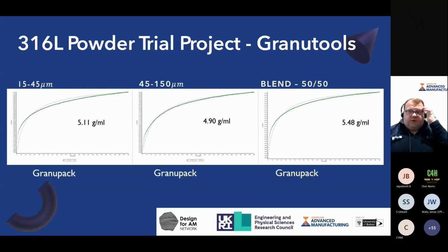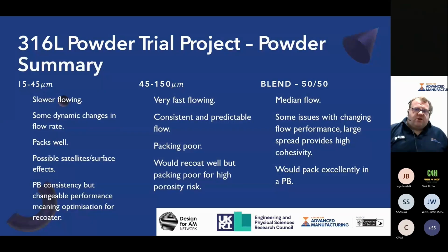And then finally, for the granule packing density, what we actually see is the peak, which again we potentially need to go back and do some more packing. It looks like the trajectory is showing it's not quite flattened out yet, so we're ready for potentially a little bit more packing. The 15 to 45 gave us 5.11 grams per milliliter. The 45 to 150, the largest powder, had the lowest packing capability. The blend gave us the best overall because there was such a large variety of powder sizes in there. So 15 to 45 was slower flowing than the 45 to 150, with the 50-50 being the median.